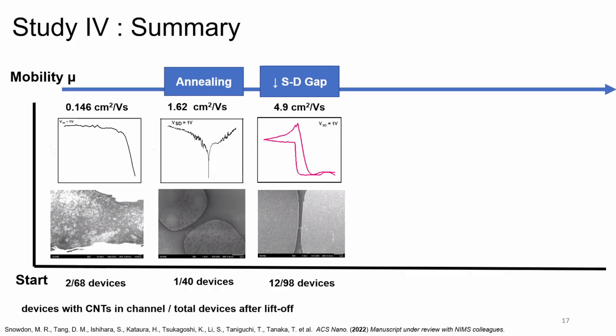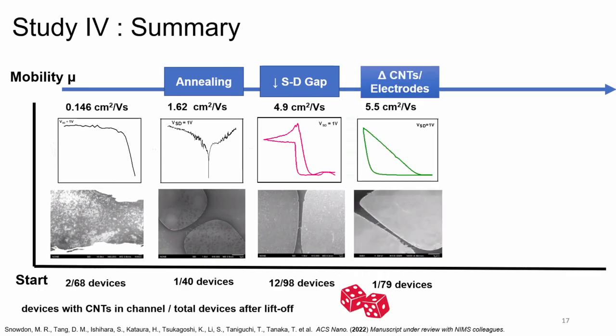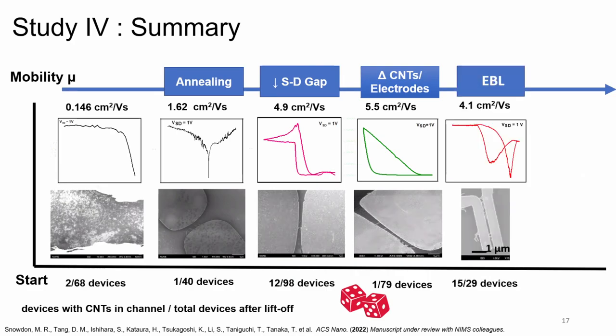And so that worked quite a bit, much higher in terms of mobility. And while I was optimizing the process, I got a lot better in terms of my successful devices. However, there was still room for improvement, I should say. And so I decided to change the types of carbon nanotubes in the solution, going from a 90% purity semiconducting mixture to almost fully 99.9% semiconducting solution. And then that seemed to have some benefits. With that, however, you can see it was still really rolling the dice in terms of what was successful and what was not. So then finally, electron beam lithography was implemented into the system.